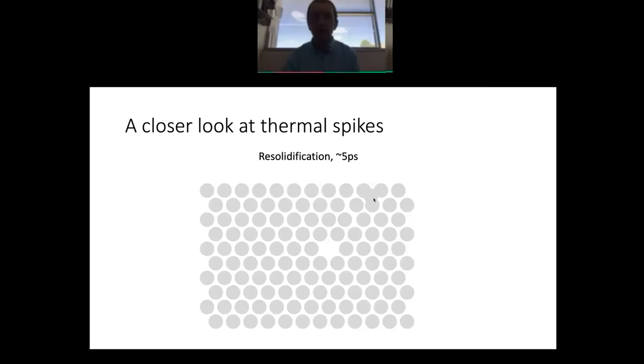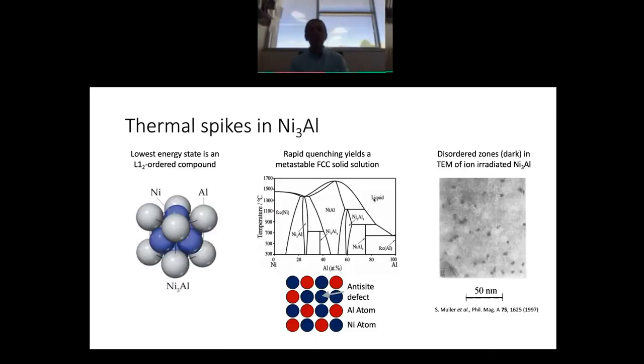Okay, so here's vignette number 1: thermal spikes in nickel-3 aluminum. Nickel-3 aluminum is an intermetallic compound. It's a very technologically important intermetallic compound. It's a very common strengthening phase in nickel-based superalloys. So it's an L12 ordered compound. This is a view of the unit cell. If you look at the phase diagram, it's not quite a line compound, so it has some width to it on the phase diagram. But in its lowest energy state, it is ordered.